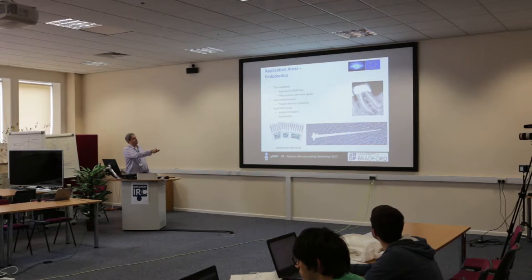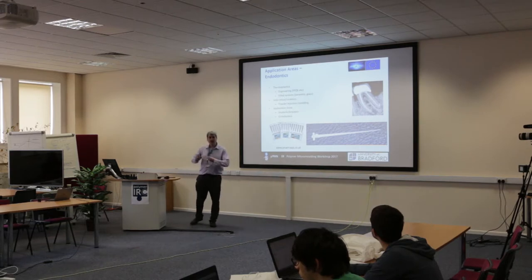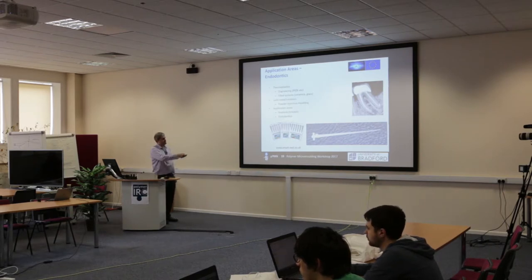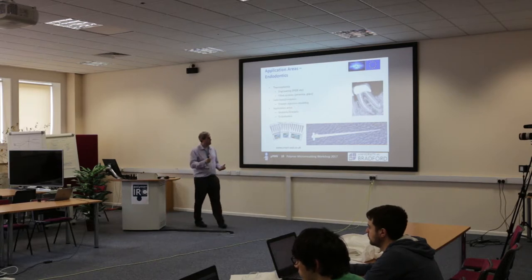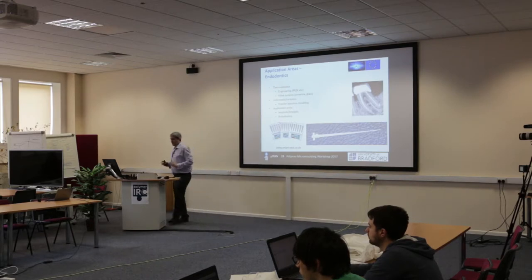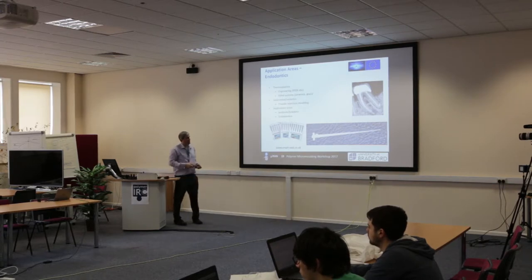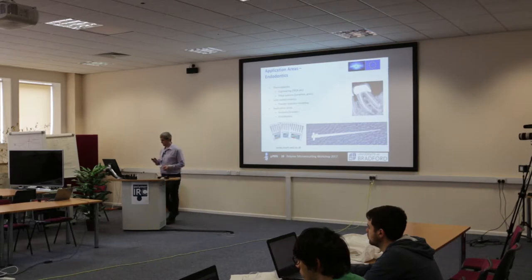The root canal core involved significant development work getting the material right — it's a two-component nylon heavily filled with zirconia. We had to look at how the material flowed to ensure process success. A coating is applied to the service core so that when it goes into a root cavity it absorbs a little moisture, swells slightly, and avoids the chance of reinfection. This was developed at the university and is now used in industry — to the tune of probably about a million components so far — and offers significant benefits over the current technology.